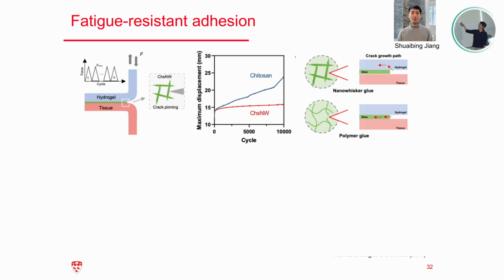As you can see, we do this cyclic peeling test, and then we monitor how the crack propagates under each cycle. You see in the case of the hydrogel, the crack slowly, gradually propagates through the interface, although the loading we apply here is very low, much lower than the adhesion energy, than the strength of this material system. But in the case of the nanowhiskers, we see this crack is stopped and doesn't propagate up to 10,000 cycles. The reason for that, we propose, is that in the case of this polymer chain case, at the interface, the crack will have stress concentration, and then under cyclic loading, this stress concentration will rupture, cleave the polymer chain in front of it.